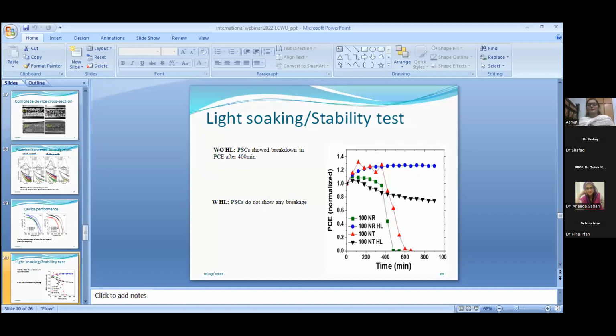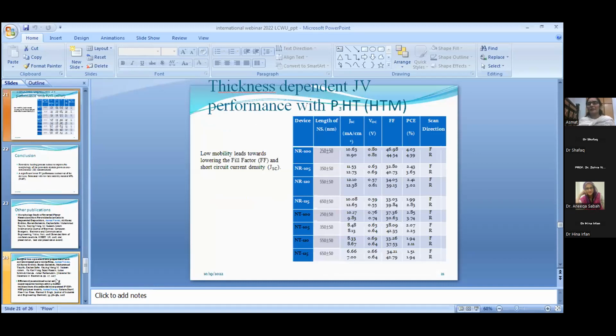Now this is the thickness dependent photovoltaic performance with our second hole transport material, which is P3HT, and you can see the efficiency is not as good as what we obtained previously using the hole transport material spiro. The similar work was done, with nanorods and nanotubes prepared from 100 minutes to 115 minutes, and the similar procedure, everything was the same, but the difference is this P3HT. Because P3HT has low mobility, which leads to a lower fill factor and power conversion efficiency.